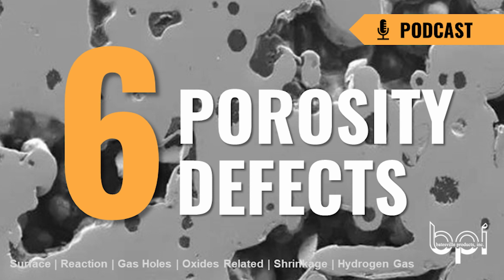All molten aluminum has an oxide layer. So if that layer gets folded in, it creates this oxide, and that's what you're seeing here. An oxide itself is really not porosity, but it changes the solidification in that area so it doesn't completely fill out. And that's why you see the porosity kind of intertwined amongst the oxides there. It's not typically a well-defined porosity as much as you see the stringers.